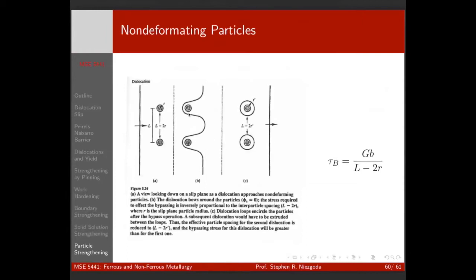So the analysis is exactly the same, right? Our effective distance that we're extruding, that we're bowing through, is the separation of the particles minus 2 radii of the particle, right? We go through, and then after we bow, we now have 2 dislocation loops left around these particles. So that effectively makes our distance smaller. So the next dislocation will be extruding through a smaller distance here, right?